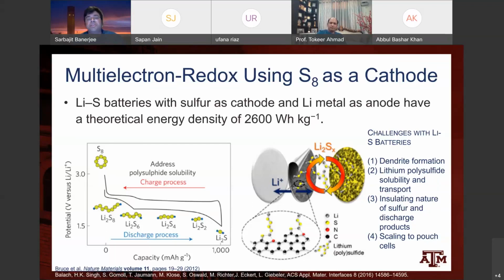So there are multiple issues plaguing the use of lithium sulfur. One is this polysulfide shuttle. These soluble lithium sulfides get dissolved into the electrolyte. They pass through the separator, and then they deposit, and they actually even pass through the SEI I was just talking about, and they will corrode the lithium metal and form all sorts of other films. Of course, using lithium metal, the dendrite formation, that entire problem still has to be solved.